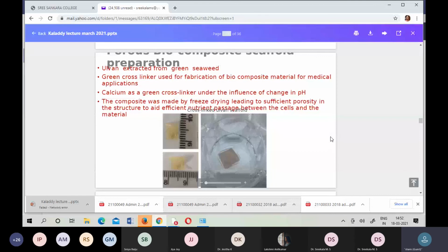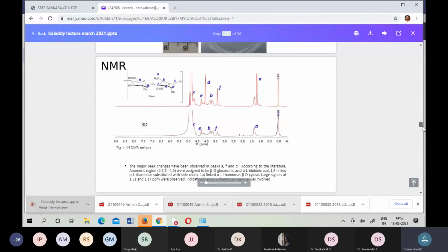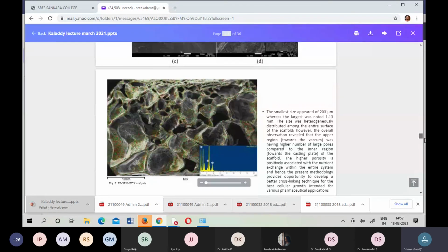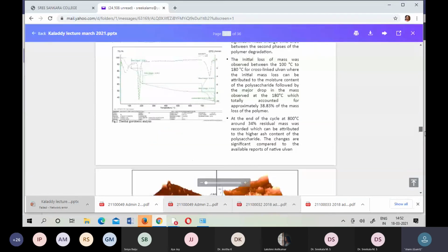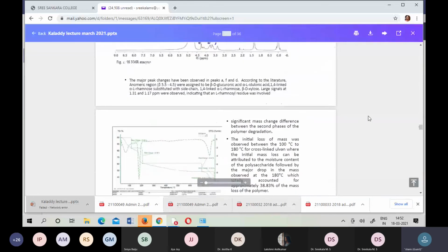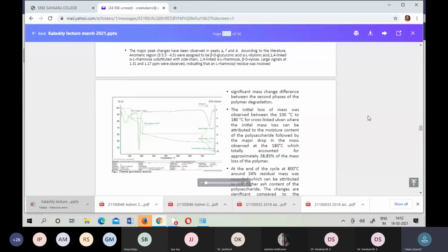And of course, we did the swelling test and water solubility and different things with the media and some commercial solvent to make sure how many days the scaffold is not soluble in water. So we compared the solubility of uncross-linked and cross-linked, and obviously the cross-linked one is more stable due to the presence of ionic cross-linking. This is again the TGA. It shows the initial weight loss is due to the moisture. The next one belongs to the polymer backbone, but here again you are getting a lot of biomass residue that belongs to ash content.